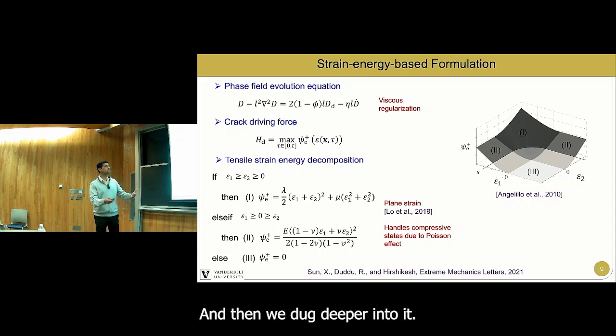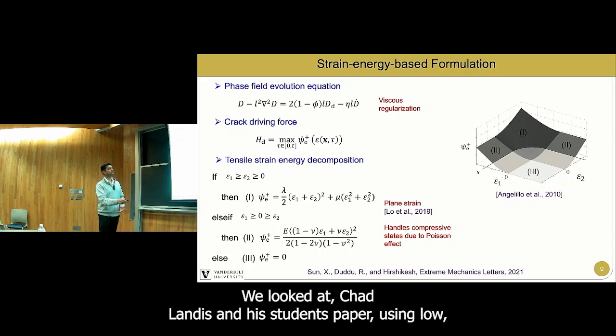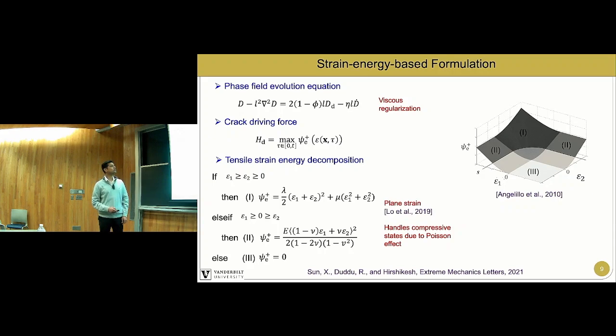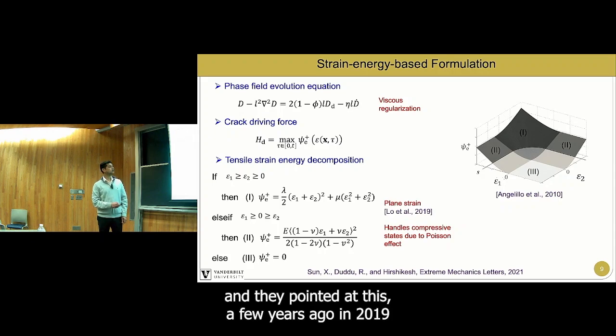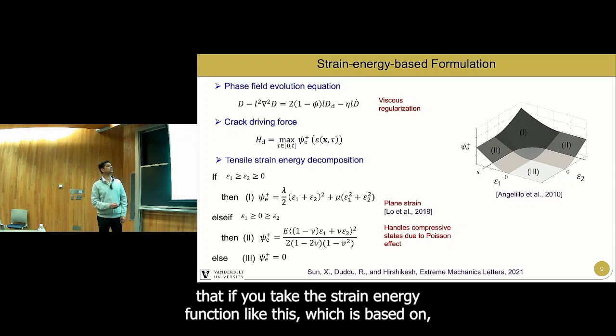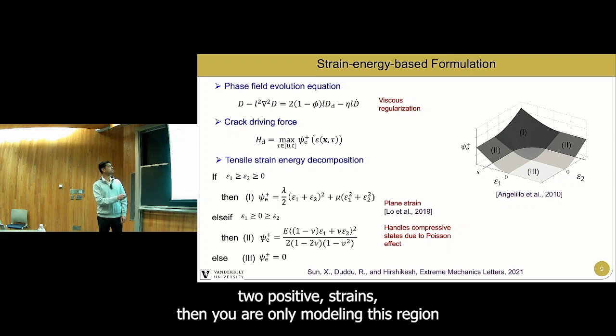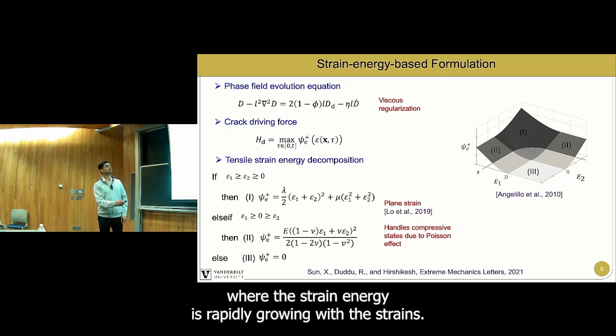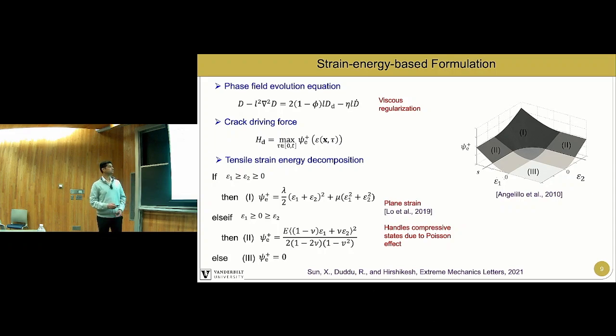And then we dug deeper into it. We looked at Chad Landis and his students' paper, Yusheng Lo, and they pointed at this a few years ago in 2019, that if you take the strain energy function like this, which is based on two positive strains, then you are only modeling this region where the strain energy is rapidly growing with the strains.